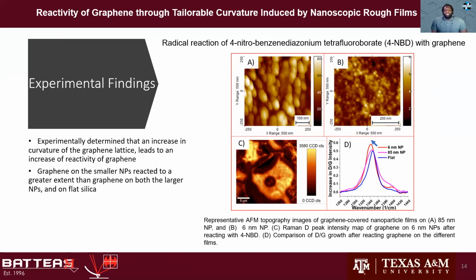Reacting these samples with 4-NBD led to an increasing Raman intensity ratio of D to G, indicated by an increase of sp3 character induced by the introduction of covalent bonds, which can be seen in panel C. So the bright areas show an increase in this D to G peak ratio. And also from panel D, graphene on the smaller nanoparticles reacted to a greater extent than graphene on both the larger nanoparticles and flat silica, which had a similar extent of reactivity.